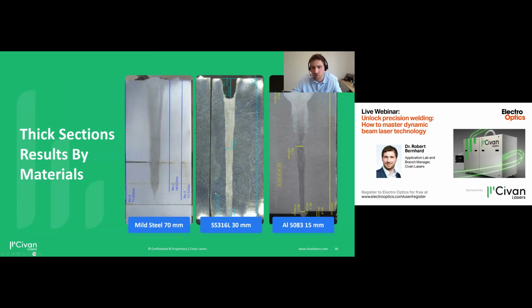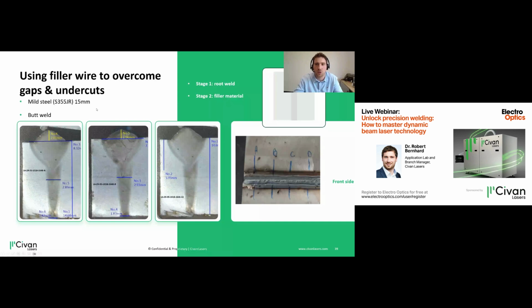On the other side, also for thinner materials with a small gap, you can see that we are able to do the weld. Here, we didn't use any filler wire. We would be able to fill the material using filler wire here. So filler wire is also a thing because of course, if we have to bridge a gap, we need some material to get there somehow. We are currently working on welding with filler material, and this is also a process that we are capable of doing. And here again, doing the beam shaping to very reproducibly melt the filler wire, it's very nice to get a process that results in a very even and porosity-free weld.